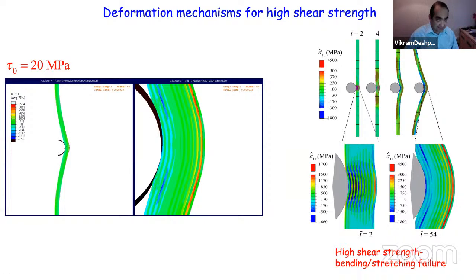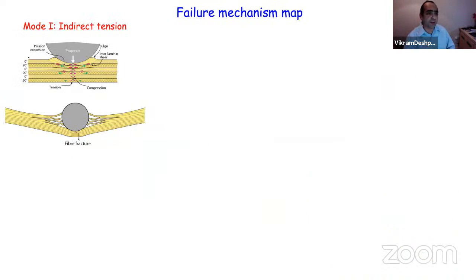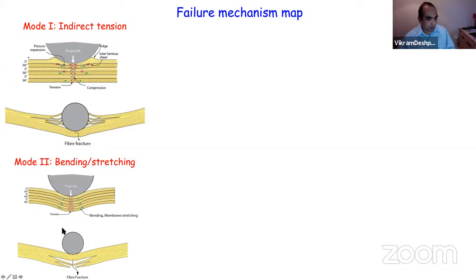To summarize, you're going to get two failure modes. One failure mode occurs at relatively low shear strengths of the beams, which occurs not by that kind of Cunniff mechanism, but by the development of this indirect tension: alternate layers of tension and compression underneath the projectile, and a failure mode which will look something like this. And at high strengths, you'll get modes in which you develop a bending tensile strength at the back of the beam, and you get failure at the back of the beam.